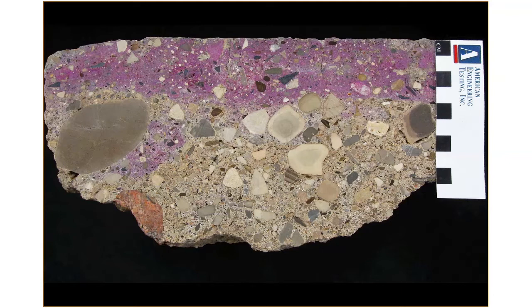And so it's very interesting that this carbonation usually happens on exposed surfaces, especially the top surfaces of concrete. And we note that this carbonation is actually on the bottom 2/3. And so this has been exposed to air for 125 years, carbon dioxide, carbon gases, and moisture, and it altered this concrete paste. What we generally think is that carbonation occurs in most concretes at about 1 millimeter a year, or 1/32 of an inch a year. So note that the carbonation is very negligible at this top surface.